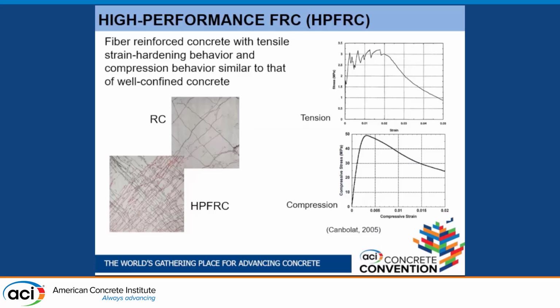Compared to fiber reinforced concrete without bars, which gives a single crack, reinforcing bars cause multiple cracking due to interaction between the bars and concrete. But comparing a reinforced concrete member with a high-performance fiber concrete member, you get a much denser network of cracks, meaning deformations are distributed more evenly, as opposed to just reinforced concrete where you need larger crack width. So you have a lot more tolerance to deformation with these materials.